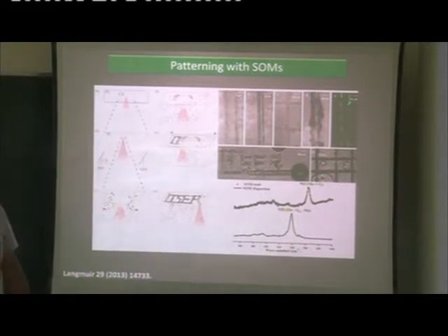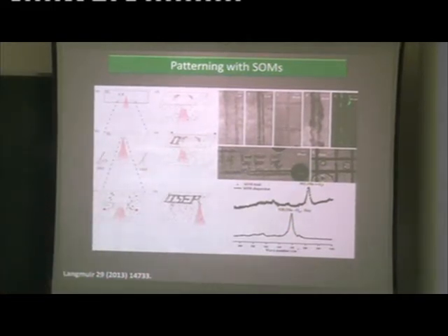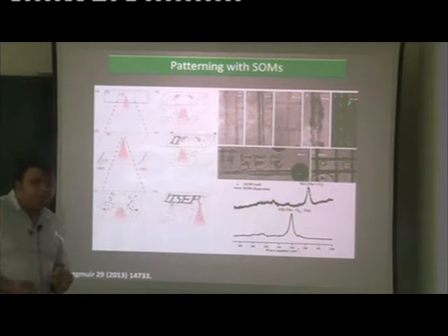Now, as you have more and more absorption of light by the soft oxometalate, the bubble starts to grow, to expand. And the kinetics of expansion of this tiny bubble into the big bubble follows Ostwald ripening kinetics, which means that if you plot the log of hydrodynamic radius against the log of time, you end up with a slope of 0.33. This is very typical of Ostwald ripening. So we found that you have an Ostwald ripening regime and you have formation of this big bubble.